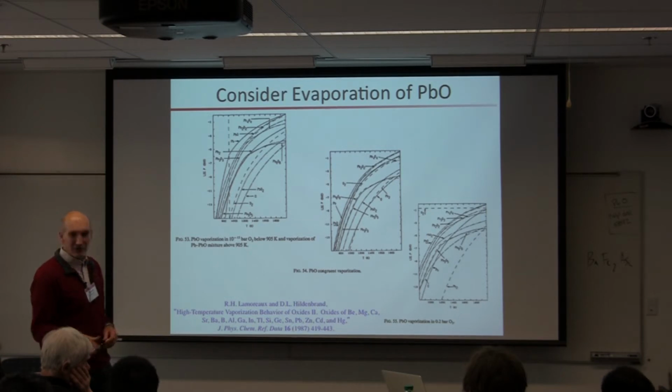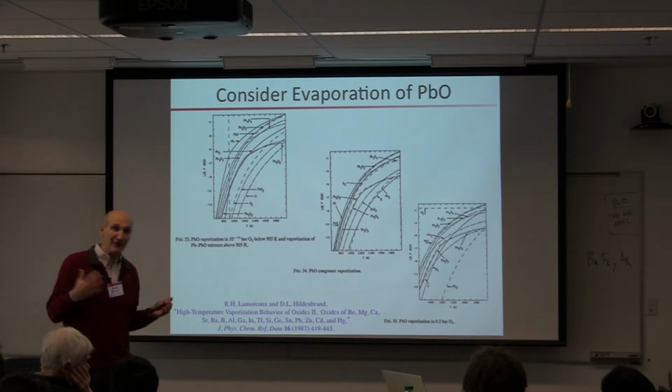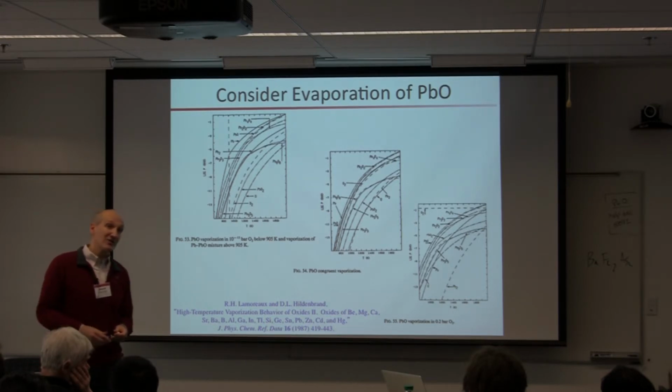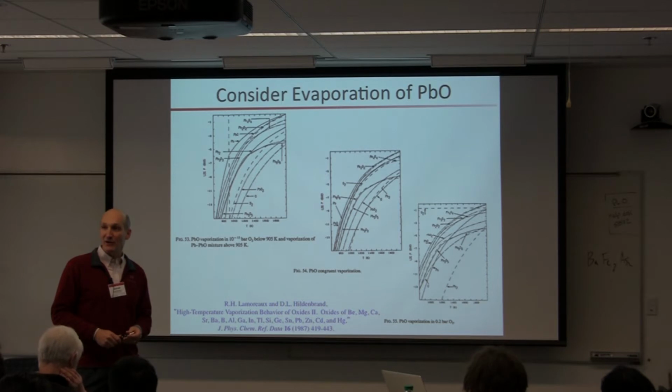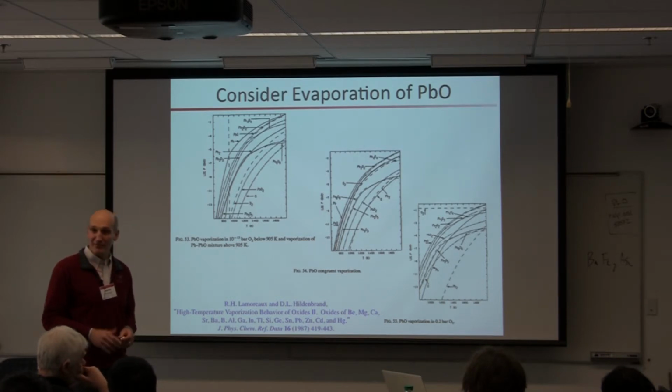I should point out, just in terms of purities, so you're thinking, okay, I'm going to use an elemental source. What's the common purity of an elemental source? Many sources for semiconductor use, you can get to 8 nines purity, meaning 99.999999 and more nines after that. It's really, really pure. For a lot of less mature materials, like you might be using for quantum materials, say vanadium, 4 nines is fantastic vanadium today. So the purities can vary drastically. Everybody got the general picture?